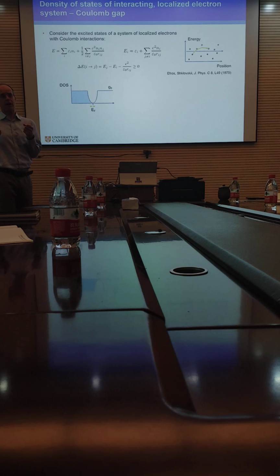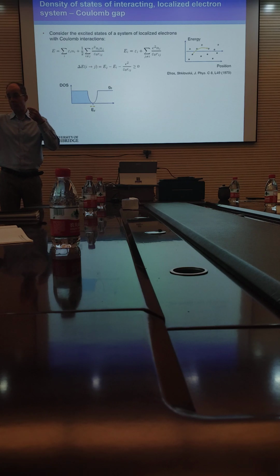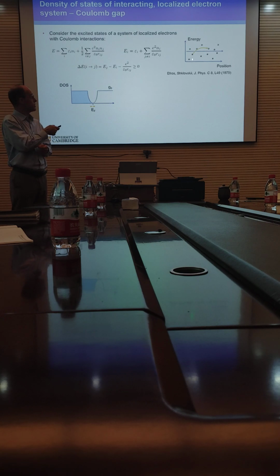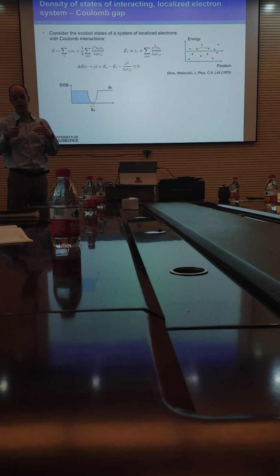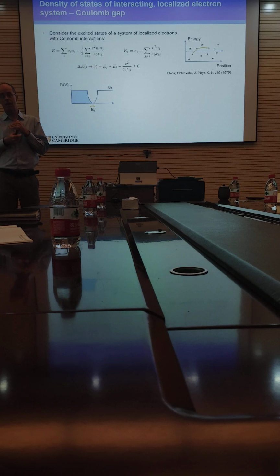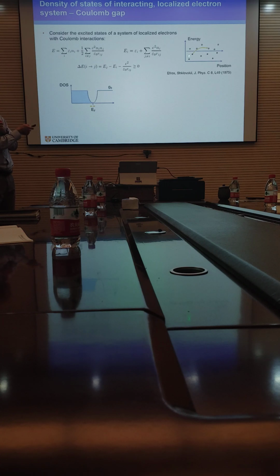And that electron-hole interaction is negative. It stabilizes the state. And if this site is close to the original site in position, then that stabilization can be quite large, because the Coulomb interaction decreases as 1 over r. So if the final site is close to the initial site, that stabilization could be significant. So the total excitation energy is the sum of this energy difference here, plus this stabilization from the electron-hole interaction. And so if the neighboring site is quite close, that could be negative. The sum could be negative.